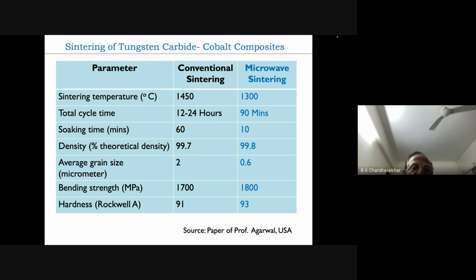The average grain size that we talked about, when seen under a microscope, is typically of the order of 2 micrometers. What it means is the starting material of the tungsten carbide should be very, very fine, maybe submicron, then it becomes about 2 microns. So then we have a bending strength and the hardness.